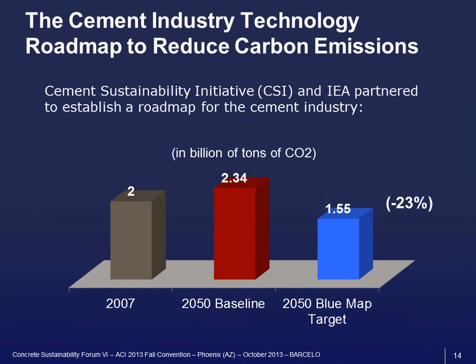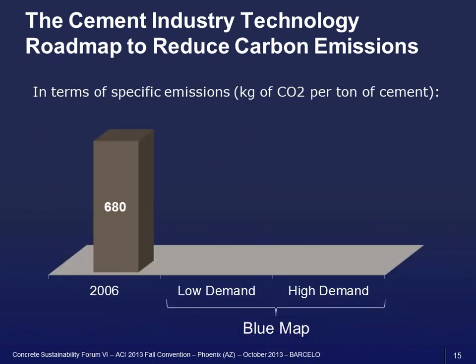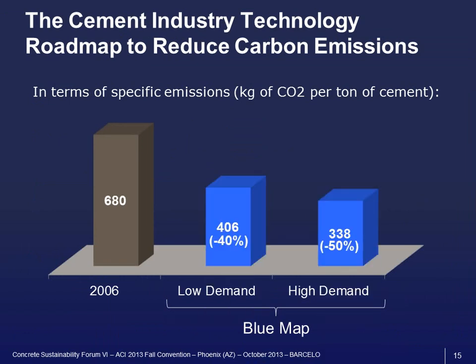So it's a 23% reduction compared to 2007 over 43 years. So you could say that it's not a huge effort, but you need to factor in that during the same time, the cement production is going to increase by 40 to 50%. So when you factor this in, you see that per ton of cement, the CO2 emission is expected to go from 680 kilos of CO2 per ton of cement to somewhere between 300 to 400 kilograms of CO2 per ton of cement.